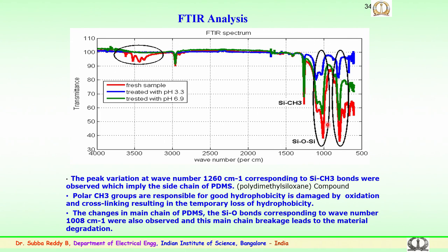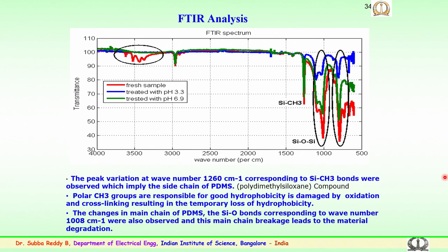The magnitude variation with pH values is clearly shown — red for fresh, green for pH 6.9 treated, and blue for pH 3. As the pH value decreases (higher acidity), the chain breakage leads to much more material degradation. A similar trend was seen for several of the samples experimented upon in this FTIR analysis.